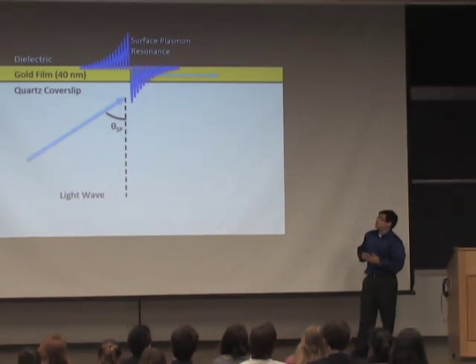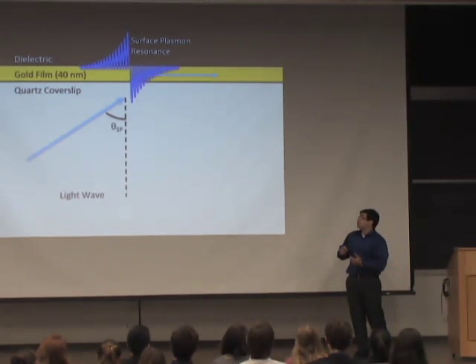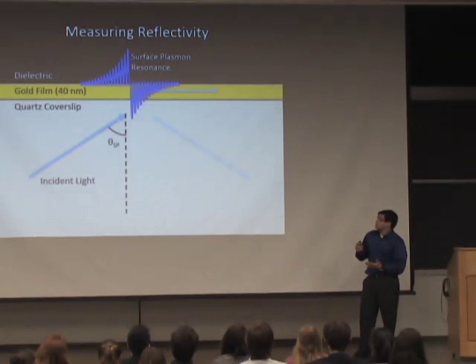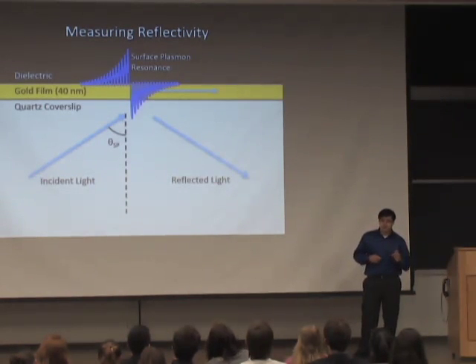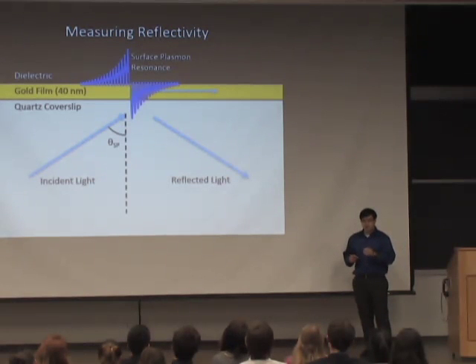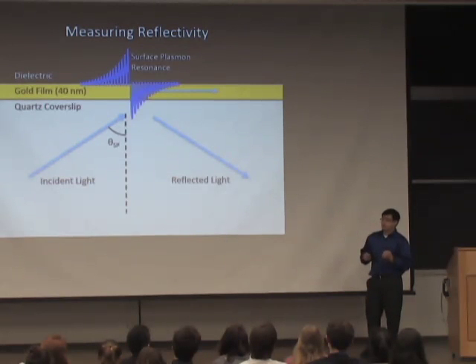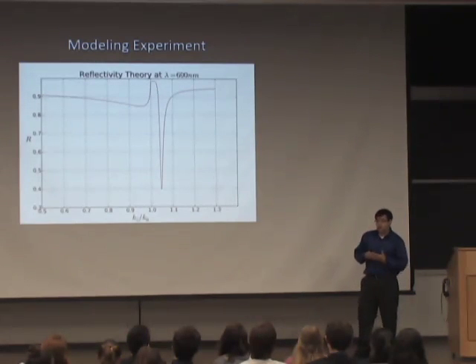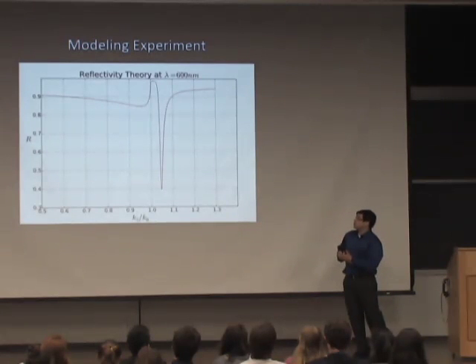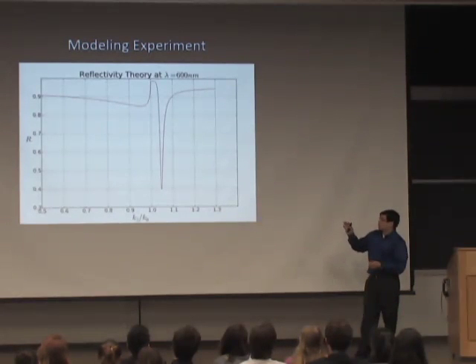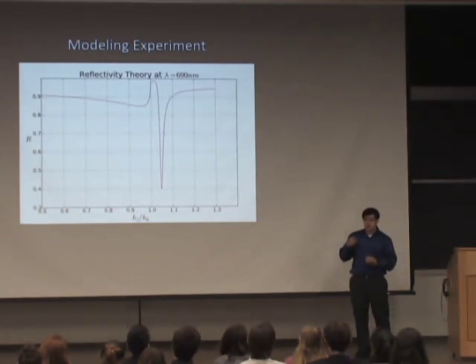So how do we know what's going on and figure out how the light interacts with the gold film? We can take reflectivity measurements and look at the reflected wave of light. Now, at the surface plasmon resonance, the energy of the light wave goes into exciting these oscillations in the charges, so we get much less reflected light. We're looking at a model of what should happen in the gold film. We see that K parallel over K naught is just a representation that is a little more delineating in our experiments of angle of incidence.